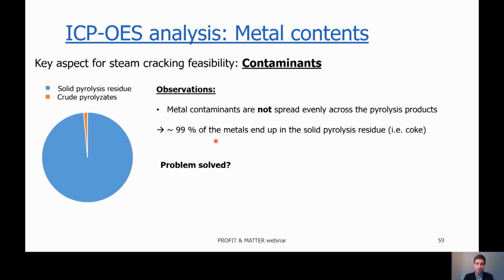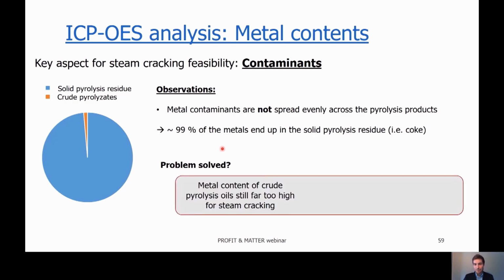The question now is: is that already solving the problem? Have we already lowered the contaminants in our liquid pyrolysis oils far enough to use them as a steam cracking feedstock? Unfortunately not. The metal content of crude pyrolysis oils is still far too high for steam cracking.